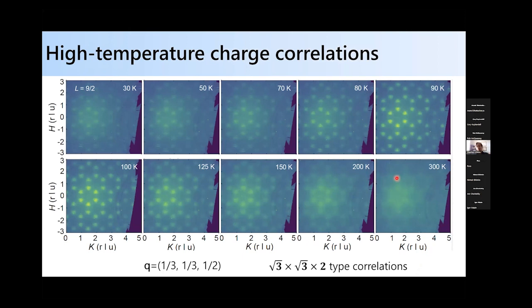So if you look at high temperature, again, the charge order transition is at around 90 Kelvin in this system. But at high temperature, this is in the L equals nine half plane. So this is the wave vector corresponding to the DFT predicted root 3 by root 3 by 2 structure.